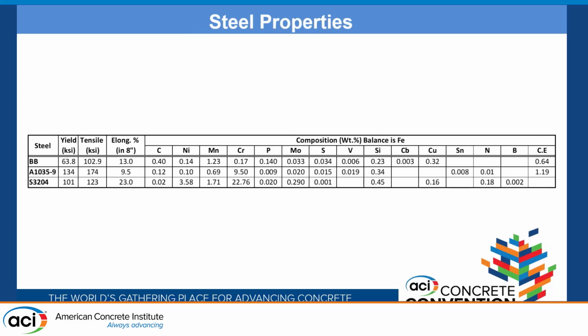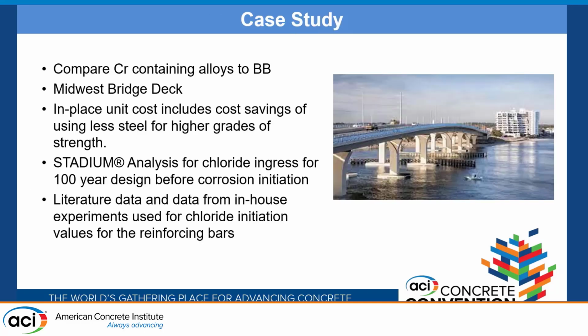The black bar, you can see the composition, no chrome in it, it's an impurity. You get to the 1035, you can see it's up to 9.5% chrome. In this particular alloy that we looked at, if it got up above 10%, then we'd be calling it a stainless steel, so it's got to be below that. And you can see the duplex steel has 22.76% chrome, roughly 23% chrome in it. It's got higher other alloy contents in it, so it's a more expensive alloy to produce. But obviously, you do get something for the extra materials in there.